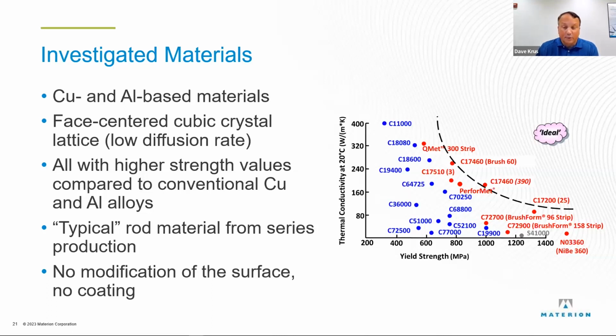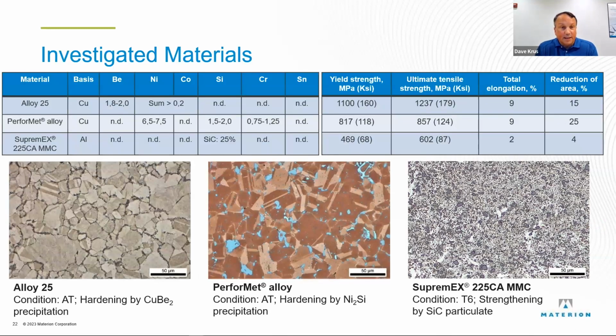I won't go too much into the graph of the properties, but talking about getting a little more materials techie here, for as much as I am able to do that. The alloys or the materials, you've got the copper beryllium, which I mentioned is 2% beryllium with some addition of cobalt. It is the strongest in a bulk form and something that you could use for engine components like a rod or a tube to make valve seats. It's the strongest commercially available copper alloy. And then the PerforMet, with a lot more thermal conductivity, is still quite a bit stronger than your average copper alloy.